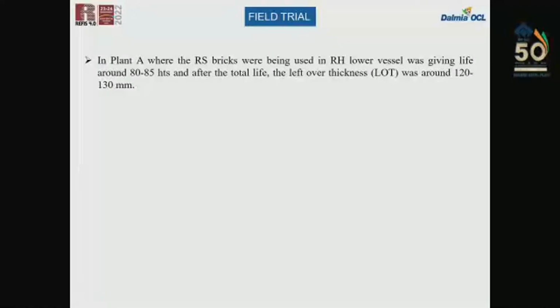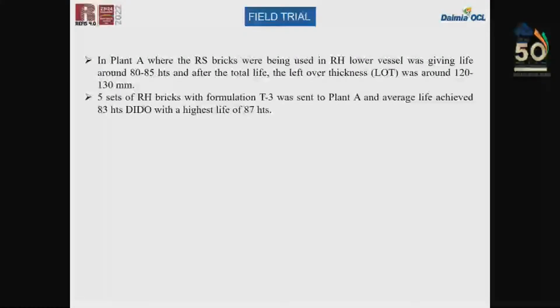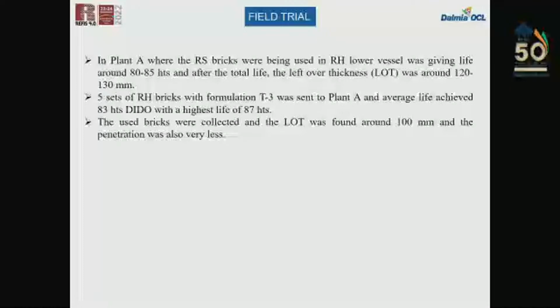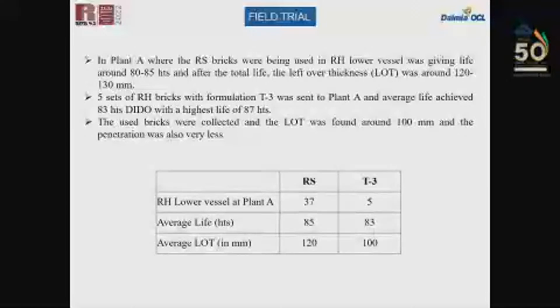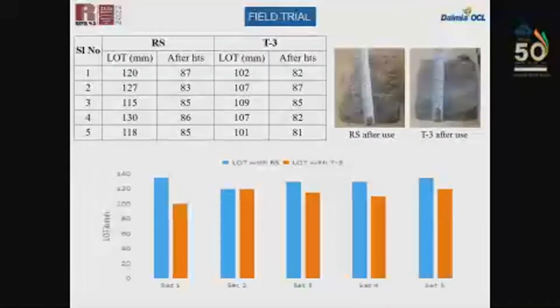Regular 100% virgin material was giving a life of around 80 to 85 heats with a LOT, that is leftover thickness, of 120 after use. We have used the same, and the total life is around 83 average with a high of 87. The average LOT is around 100, which is okay because the lower vessel life almost depends on the life of the snorkel. In that plan, the snorkel life is taken as around 80 to 82 heats. So these are some data. We have an average life of 83 with an average LOT of around 100.